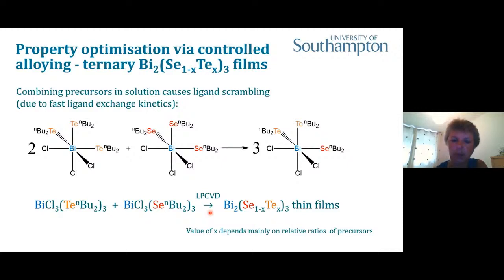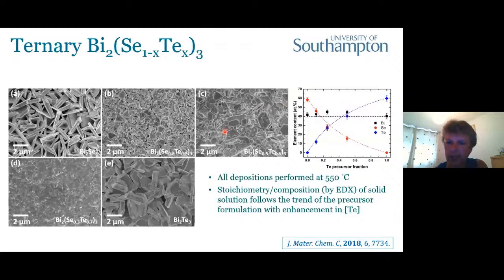We can use this in a similar approach and generate these ternary phases where we have a variation in the selenium or tellurium ratio depending on how much of each of the precursors we use. And again, just to illustrate this in terms of the structures, depending on the composition. So we've got the 2 extremes. This is bismuth selenide, the binary material, and bismuth telluride, the other extreme binary material. And then we're just showing some examples of different ternary compositions within that.